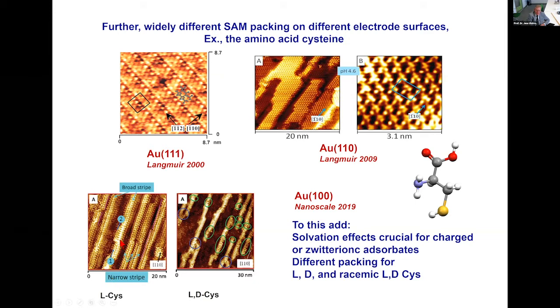And here some of the very recent data. This is gold 100 that seems to pack in a very strange way in long stripes, which is perhaps surprising, because if one considers the actual structure of the gold 100 surface, there are no indications of stripe formation just from the electrode surface. It is also interesting, the enantiomers of cysteine, L and D, give virtually identical packing on the surface, whereas the racemic mixture gives a more rugged kind of packing. It is as if the two enantiomers are somehow in each other's way, and they form kinks and other irregularities.